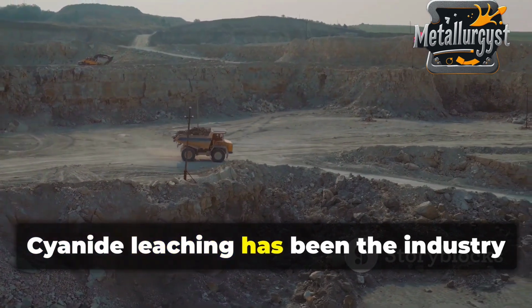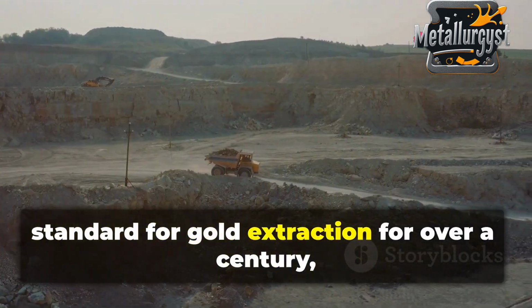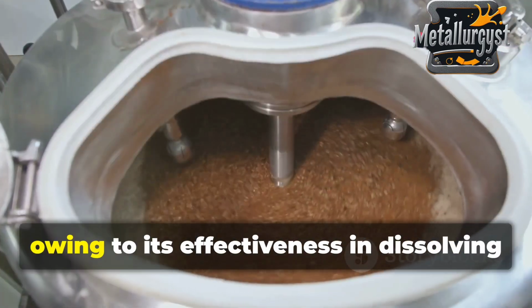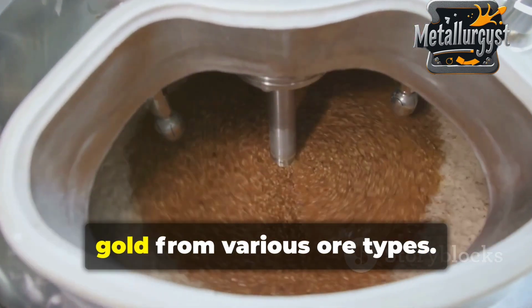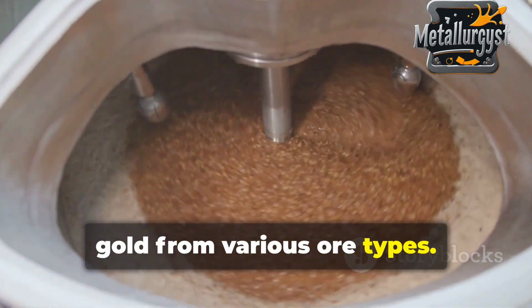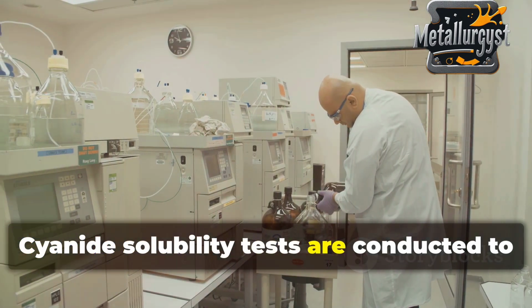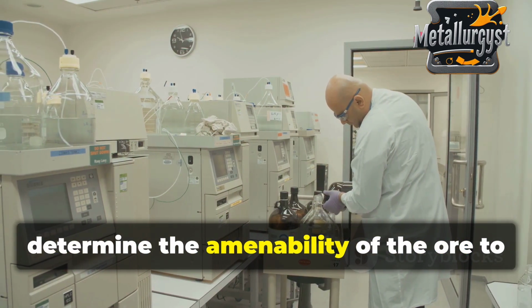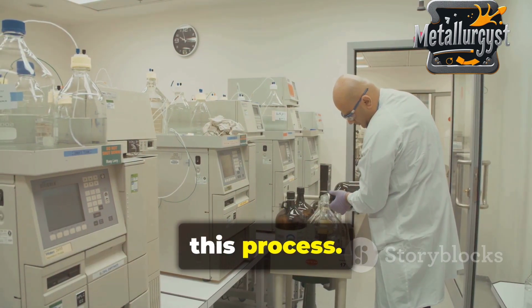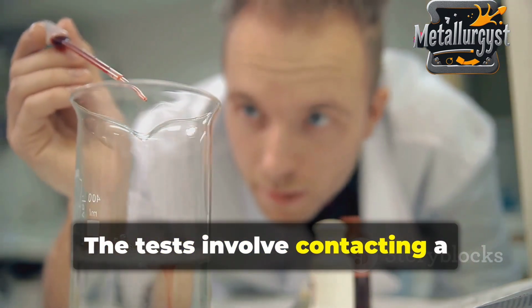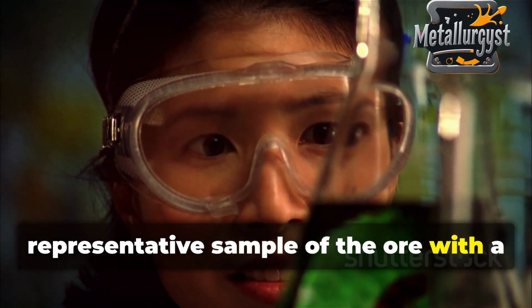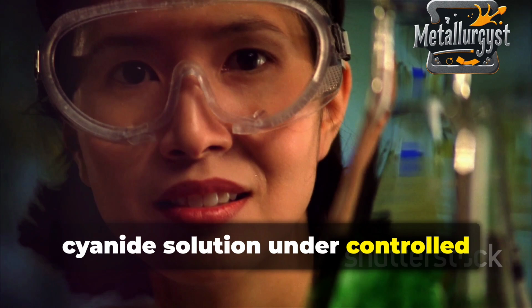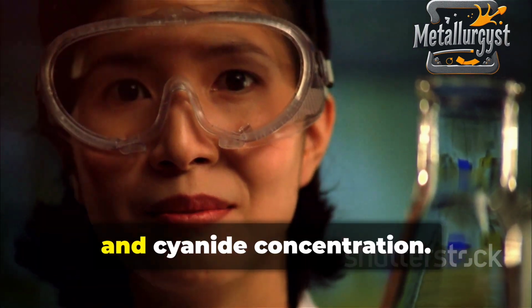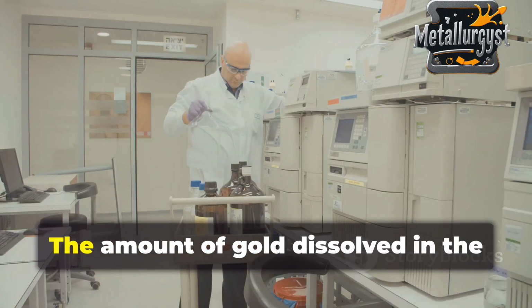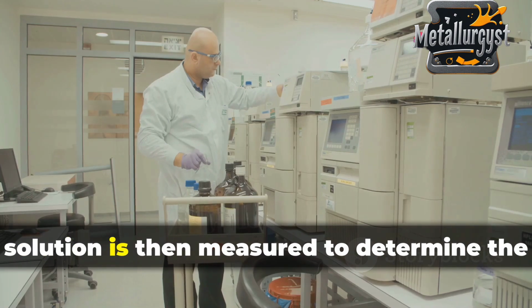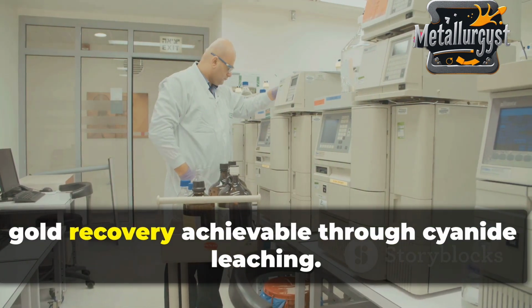Cyanide leaching has been the industry standard for gold extraction for over a century, owing to its effectiveness in dissolving gold from various ore types. Cyanide solubility tests are conducted to determine the amenability of the ore to this process. The tests involve contacting a representative sample of the ore with a cyanide solution under controlled conditions of pH, temperature, and cyanide concentration. The amount of gold dissolved in the solution is then measured to determine the gold recovery achievable